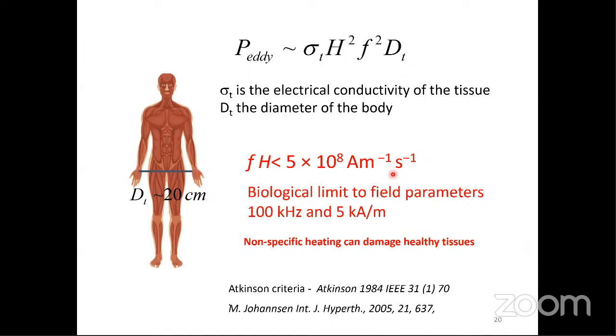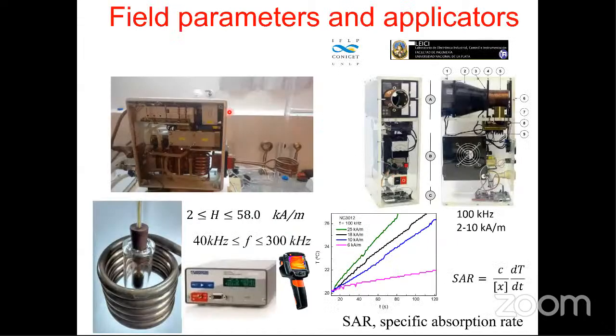I always like to show our applicators. This is a commercial one that has a nice range of fields and frequencies. You can choose whenever you like. And we also have this one that was constructed in La Plata that can be used for in vivo and in vitro experiments. So we can measure this specific absorption rate parameter, which tells us how good the nanoparticle is at taking energy from the electromagnetic field and dissipating it in the sample, in the tumor, as heat.